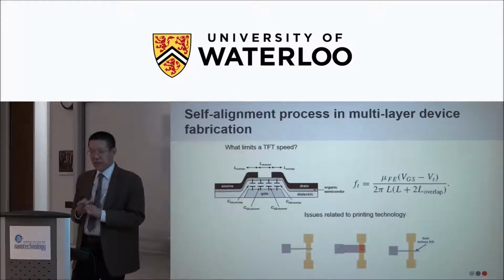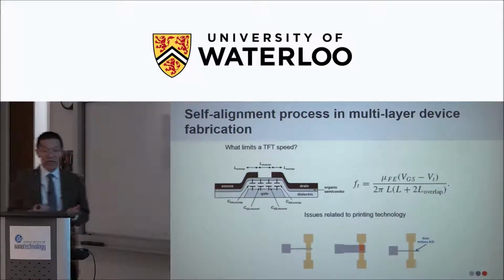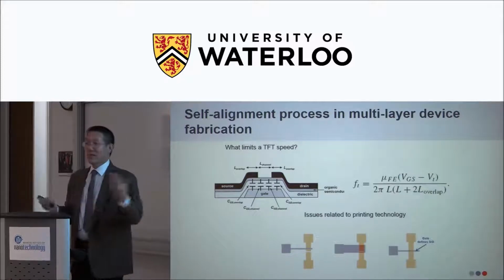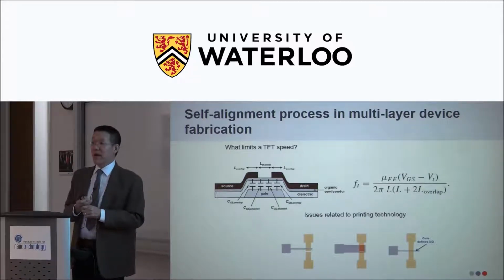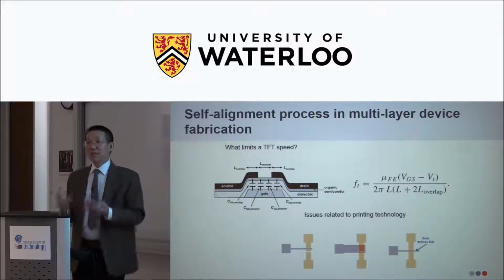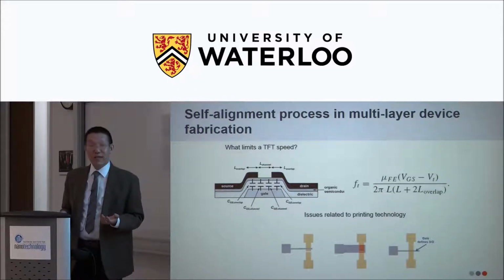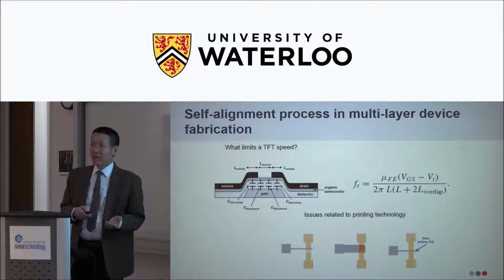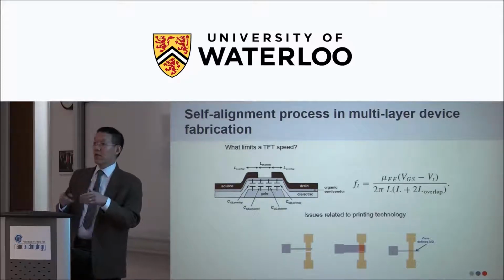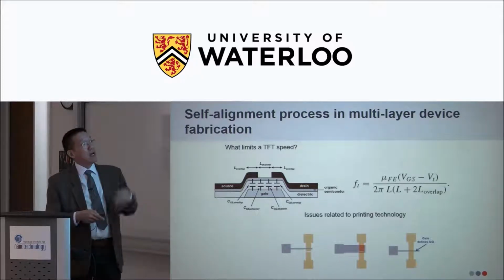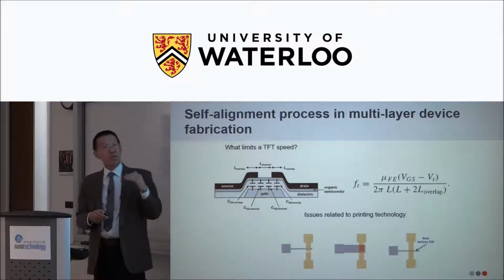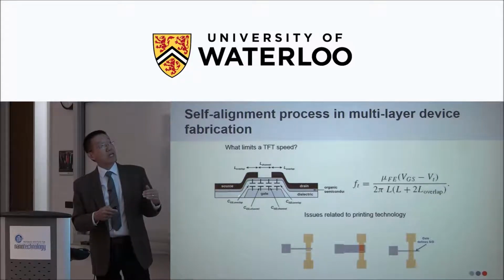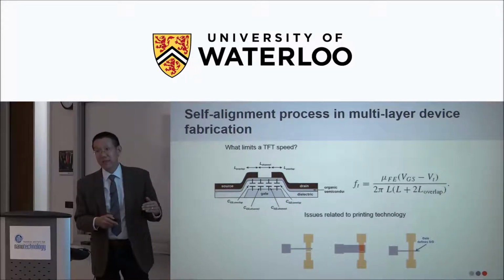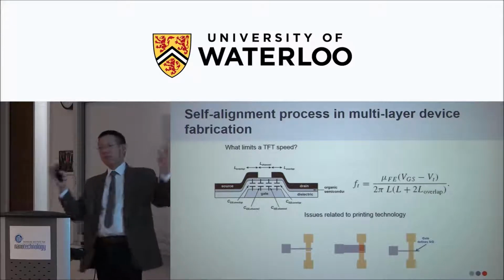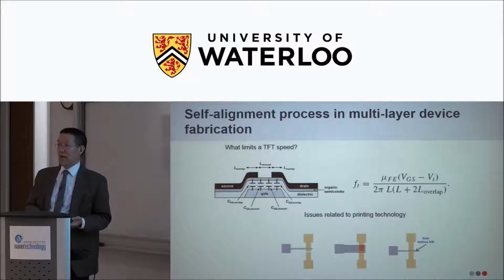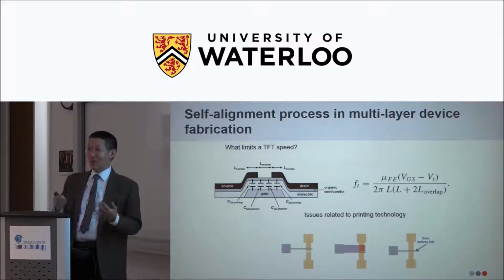Another challenge in printed electronics, or for making transistors, is alignment, as I mentioned. Even the best machine we have at NRC now is plus or minus 10 micrometers from layer to layer. That means the channel you want to make needs to be at least 20 micrometers, right? Or you print really wide gate electrodes to cover your source and drain to avoid missing the channel area. But the transistor speed will suffer if you make too much overlap between the gate and the source and drain electrodes, because the overlap capacitance will increase and your device will be slower. With a low mobility, the device will be really, really slow.